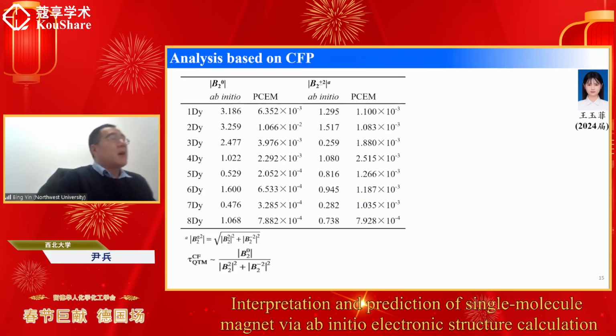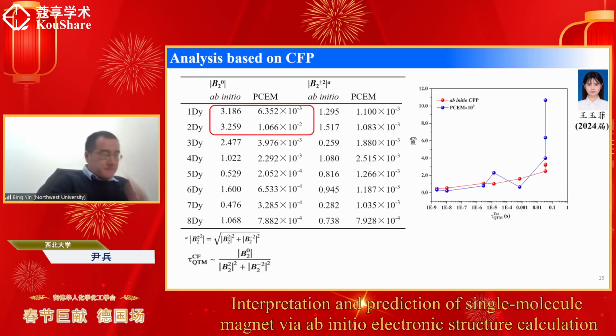And in this classification, we could give ab initio crystal field parameters as well as PCM crystal field parameters. Of course, the PCM crystal field parameters are not very accurate, only semi-quantitative, but we can see that both the accurate ab initio ones and the semi-quantitative PCM ones give the same general trend.